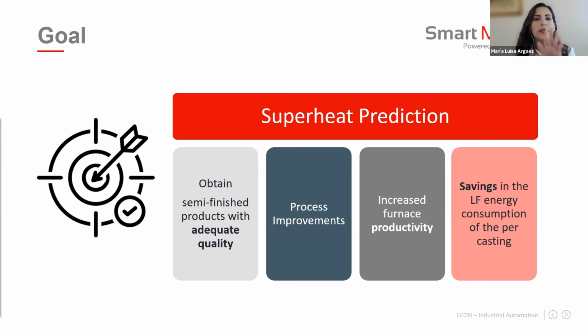For example, obtain semi-finished product with adequate quality, avoiding the presence of defects such as cracks and accumulation of pores. Increase furnace productivity by saving time losses that unnecessarily high superheat entails, and making production more efficient by avoiding material discarded due to the presence of defects. Improvement in process control, avoiding variability in the superheat between heat and heat, maintaining optimum CCM speed. And savings in energy consumption in the ladle furnace per heat by avoiding giving an unnecessarily high superheat.